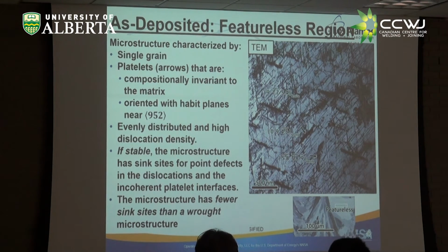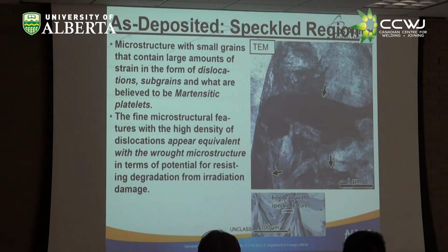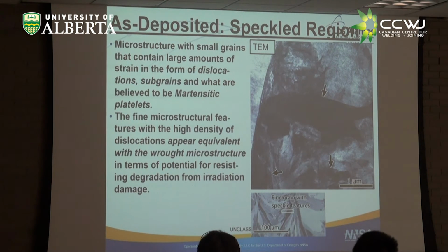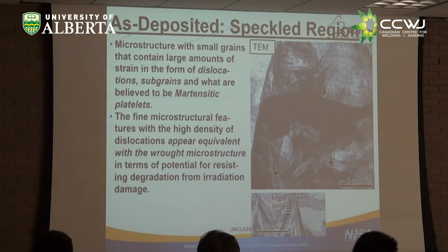But this microstructure here is still not as good as you would find if you had a martensitic structure. This same young man also did this TEM bright field, telling me that, and I don't really see much except dark and sort of mottled, but he believes that there are dislocations and subgrains of what he thinks are martensite platelets that I've yet to see, and I still want him to go back and redo this sort of thing. But similar features are seen in the wrought microstructure, the martensitic microstructure. And this microstructure, again, if stable, would be useful for radiation tolerance.